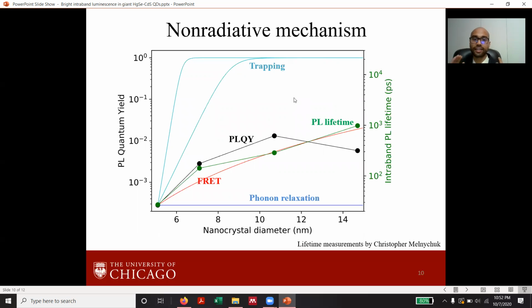Apart from getting bright luminescence, the trend of the quantum yield as a function of thickness gives a hint at the non-radiative mechanisms at play. On the estimated calculated plot that I showed at the beginning of the presentation, I have plotted the data for the quantum yields for the mercury selenide CdS along with the PL lifetime measurements recorded by Chris in our group. Though there are only 4 data points and there is some disagreement for the thickest shells, the trend strongly suggests that Förster energy transfer is the dominant non-radiative mechanism.